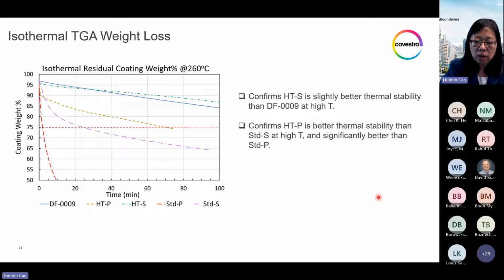This chart shows the isothermal TGA results held at 260 degrees C, where the HTS has a slightly slower weight loss rate than DF-0009, and the HTP is actually much better than the regular secondary coating, considering its modulus is 100 times lower than the standard secondary. This is quite remarkable. And of course, it's significantly better than the standard primary, which cannot survive at all in these extremely high temperature conditions. It's very risky to use this kind of coating in high temperature environments.